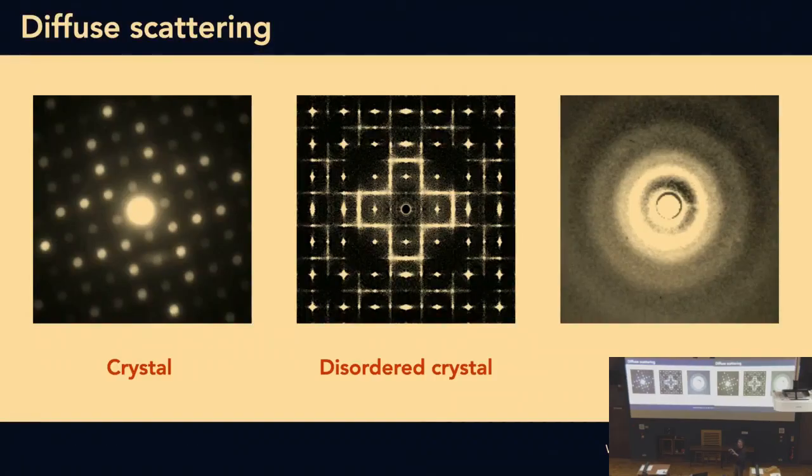They're kind of concentric rings, but there's some modulation in it. The fact that there's even that modulation tells us that in a liquid or a glass, the structure is not random. If it were window glass, for example, there'd be information about the silicon-oxygen bond length, which is well defined in silica glass, and that information is contained within it. But this diffuse scattering is very hard to interpret directly, and you can't use conventional crystallographic approaches to do so.